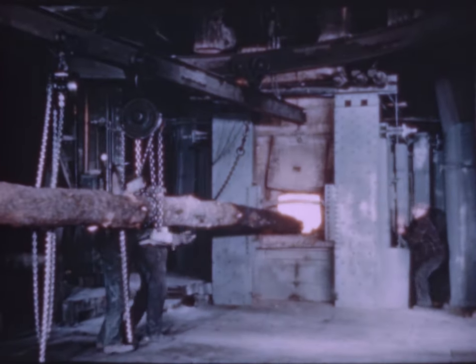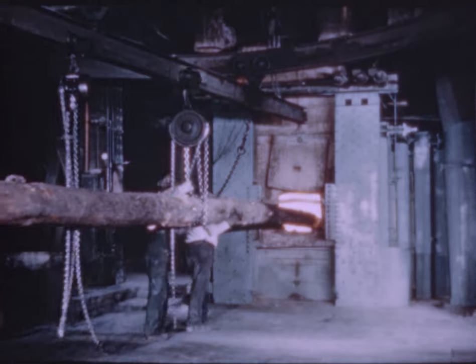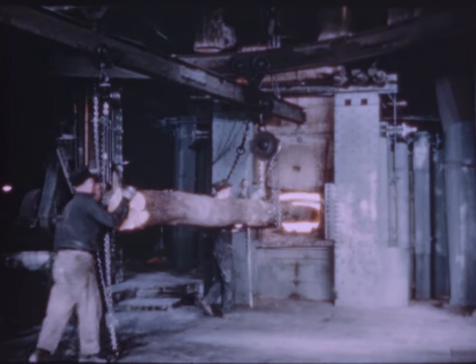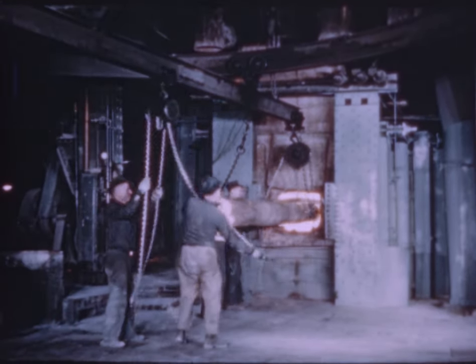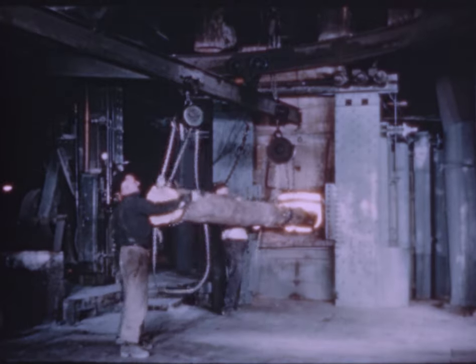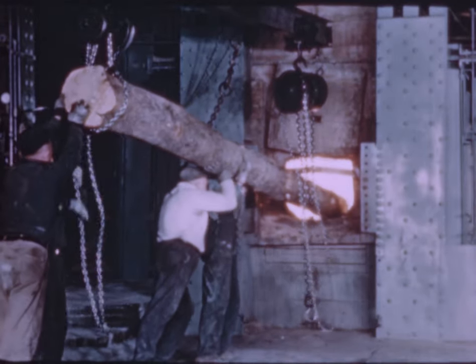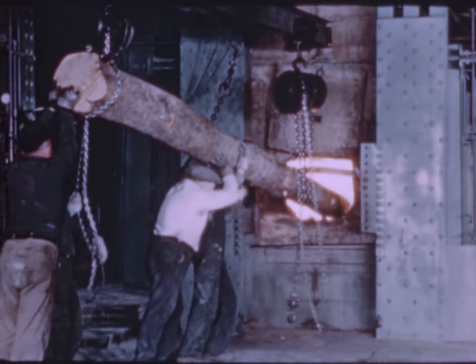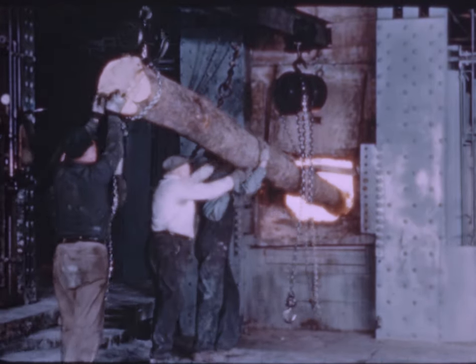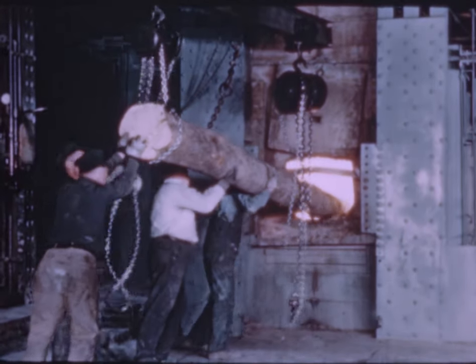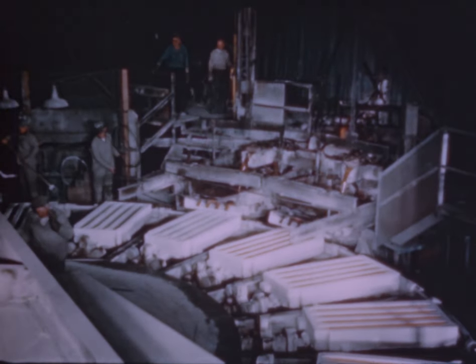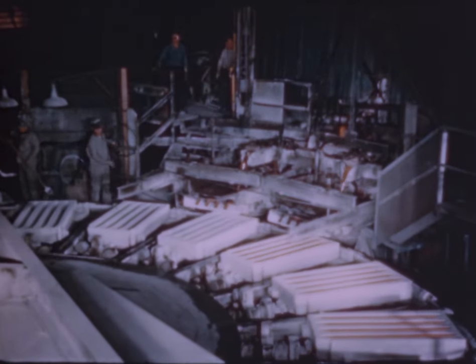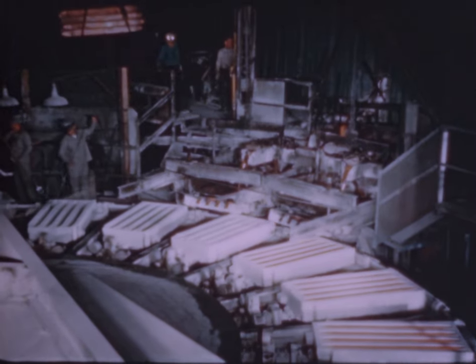To accomplish this, air is blown through pipes thrust in the molten bath. To further reduce the oxygen content, the temperature of the bath is raised and the charge covered with coke. Forcing green wooden poles below the surface violently agitates the metal and brings it into contact with the carbonaceous cover. The metal now has the most desirable chemical balance for the production of sound castings.